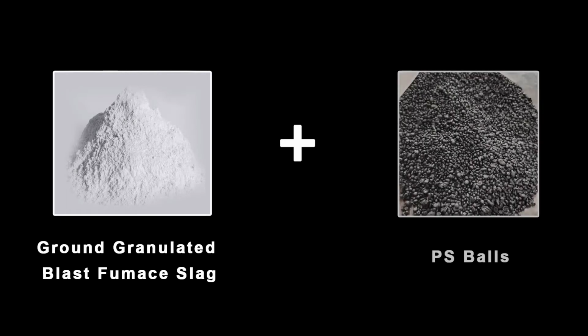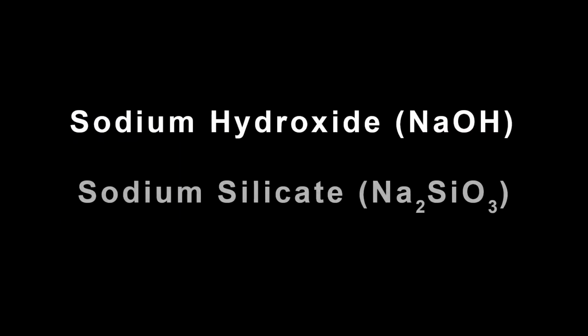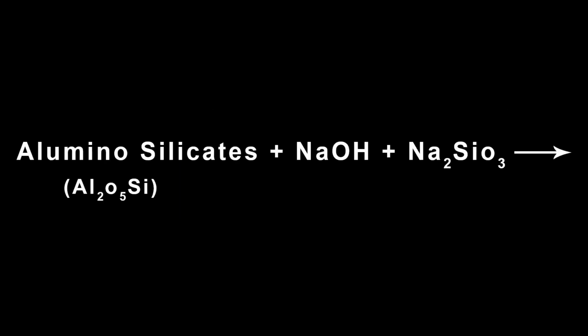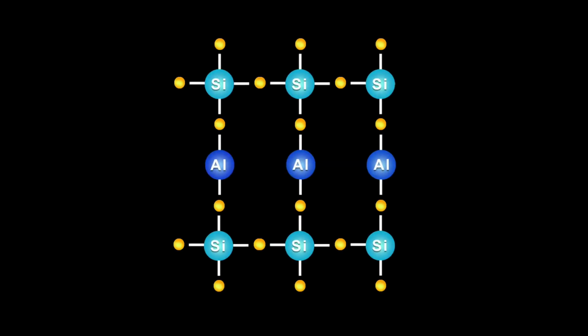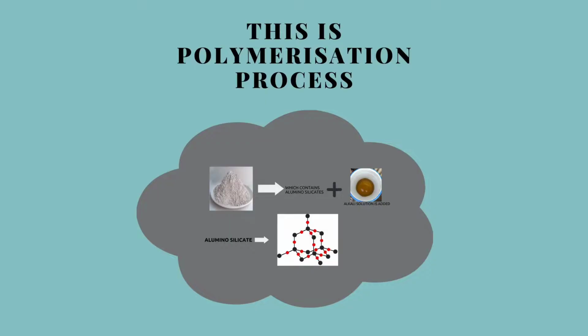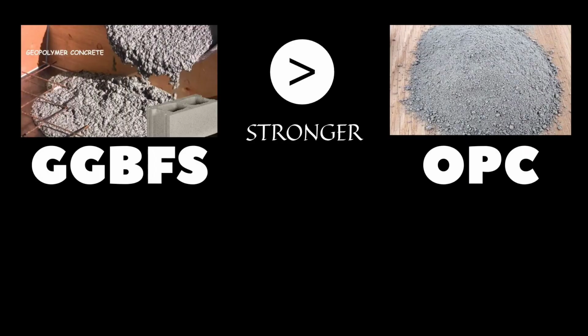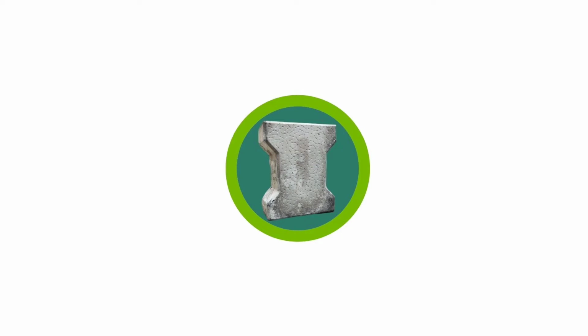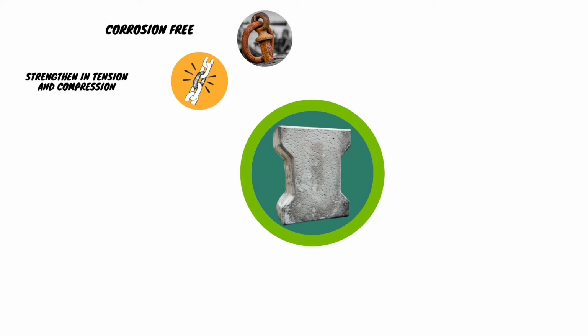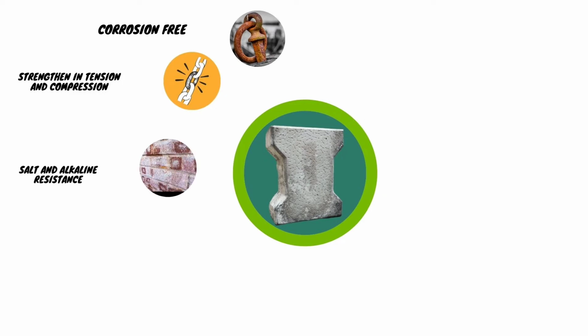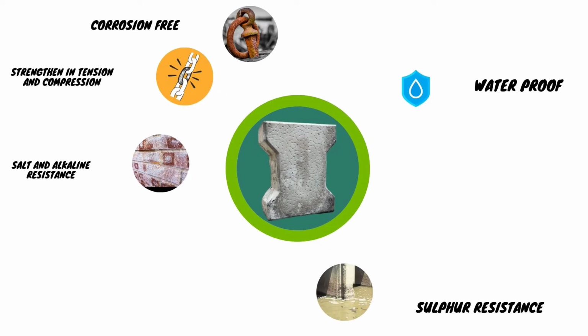GGBFS contains aluminosilicates. When the alkali solution is added, it transforms the aluminosilicate into a 3D network which is bonded by covalent bonds. This is the polymerization process, and that's why geo-polymer concrete is stronger than OPC concrete. Geo-polymer concrete has high strength both in tension and compression, is corrosion resistant, alkaline and salts resistant, sulfur resistant, with better waterproof